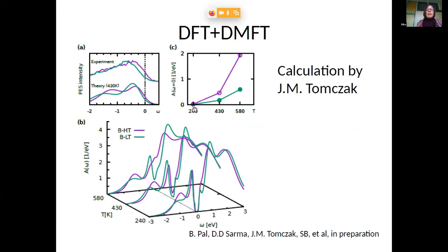Okay, so beyond the comparison at a given temperature of the spectral function, again calculated from DFT plus DMFT or cluster DMFT, what we did now was make a systematic study as a function of temperature. And of course, in theory, we can do things that experimentalists can't do. Namely, we can take the structure that is stable at a given temperature, and then investigate its electronic structure and spectral properties at any temperature we want. And so that's what we did.